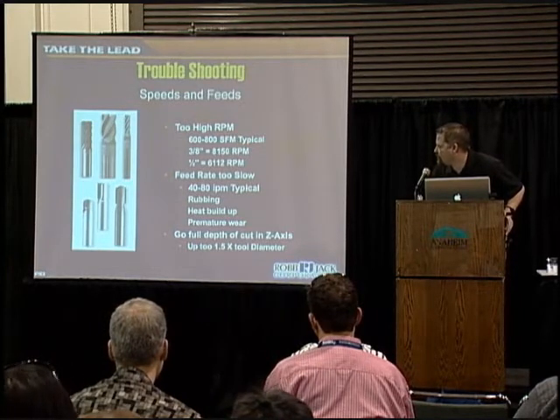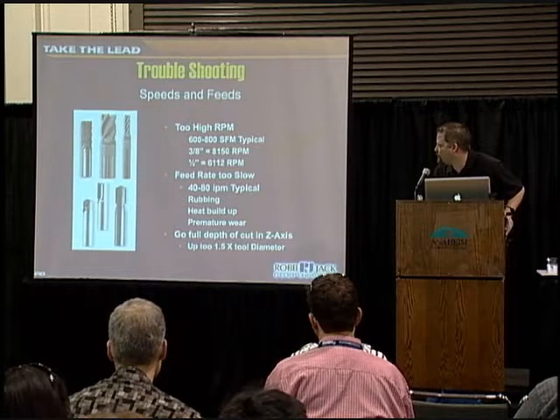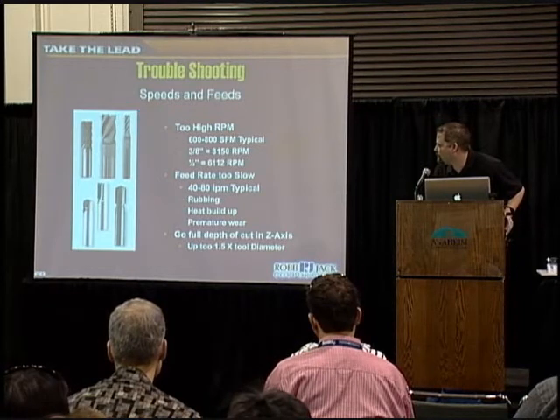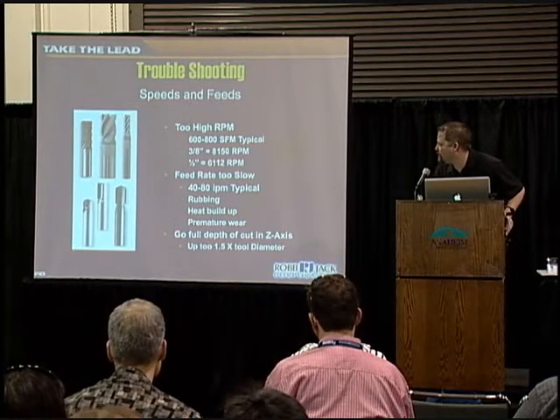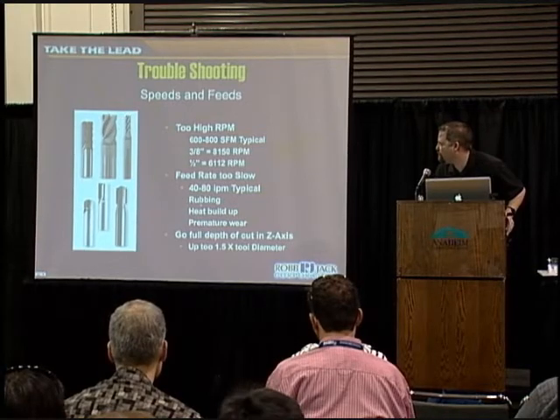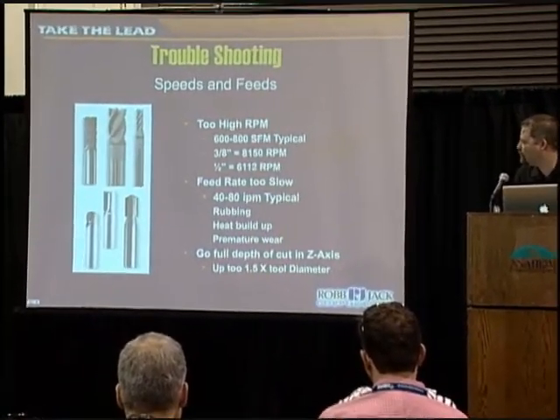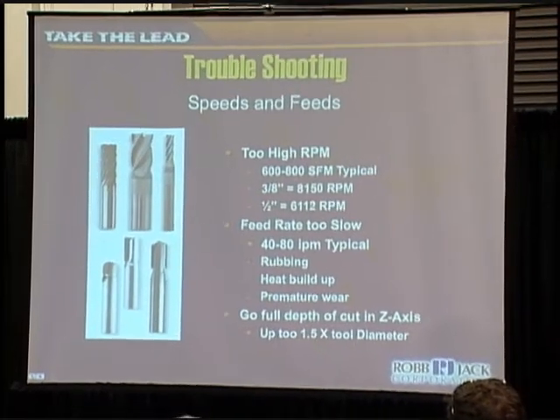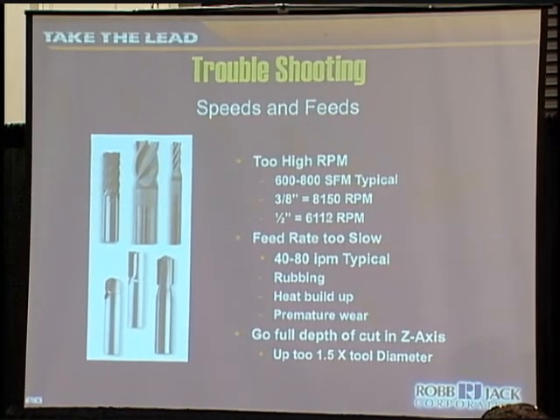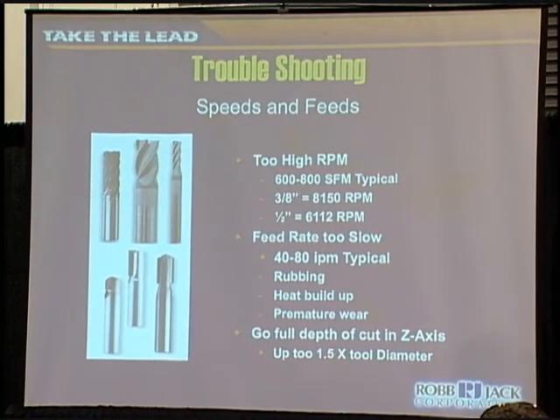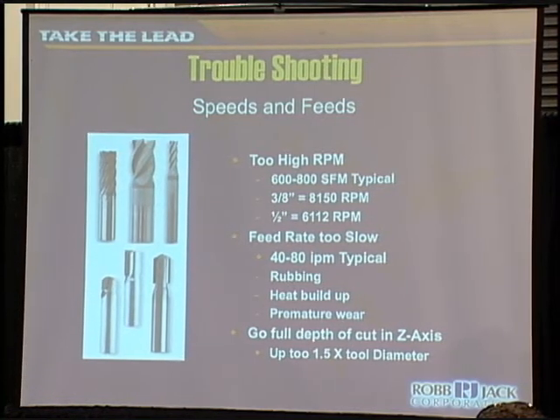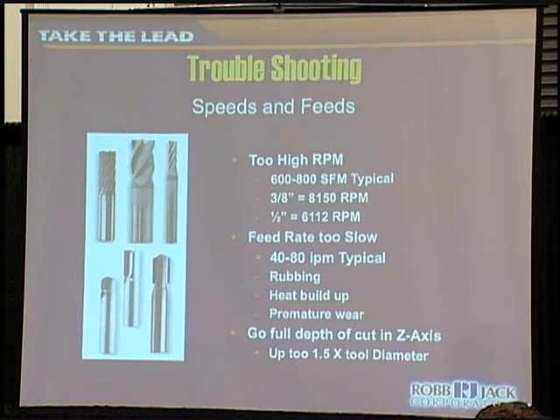As far as the troubleshooting, this kind of recaps what we're talking about. Feed rates between 40 and 80 inches per minute. You want to get rid of rubbing and heat buildup. So a 1/2-inch tool would be about 6112 RPM, and a 3/8 tool about 8150. And you want to go the full depth, and you can go up to 1.5. We have customers going all the way up to 3 times the tool diameter in Z depth to cut per pass.